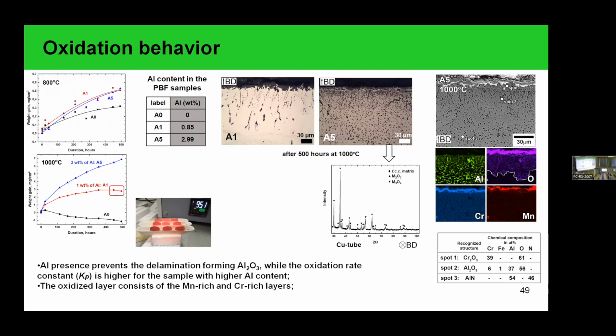It's related with the result from the X-ray diffraction analysis, and under this layer with the chromium and manganese, we observed the formation of the aluminum oxide, which generally prevents the further penetration of the oxygen in our structure and delamination of the material. But also we see here the zones enriched with alumina, and under the zone, we observe they are also enriched with aluminum and nitrogen of our material, which also demonstrates the effect of the nitrogen, which was in the initial powder only about 0.5%, on the material behavior at a higher temperature.